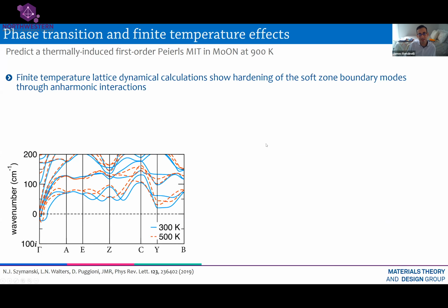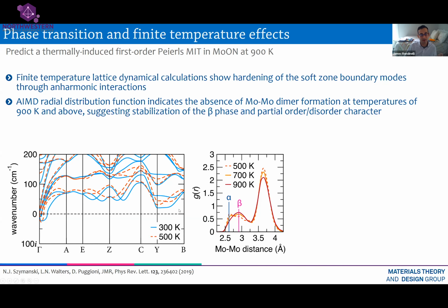Okay. And then Nathan did a final set of calculations to examine the effects of finite temperature on the stability of the material. And what we see is that there is a phase transition. This thermally driven metal insulator transition is going to be temperature dependent. So he monitored or computed the stability of that displacement as a function of temperature to track how this would thermally occur in an experiment. He did this with ab initio molecular dynamics. So he did a molecular dynamics calculation in which the forces are computed quantum mechanically to study the evolution.